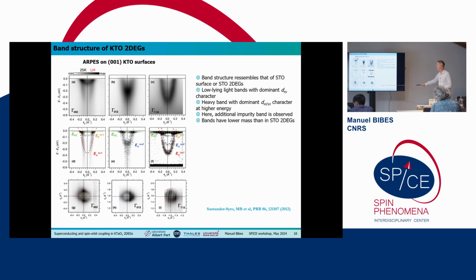So several years before that, we worked with Andrés Santander in Orsay, and we were trying to image the band structure using ARPES of this 001 KTO. And for that, we were not depositing aluminum. We were kind of breaking, not really cleaving, but kind of breaking in situ single crystals. And these are the ARPES data, which are not as crisp as you would expect in a quantum material. But in oxides, it's actually rarely the case. So the main features that were identified were the presence of different types of bands, a relatively light band here, with a slightly higher mass pair of bands here, and some states here with a very, very high mass.